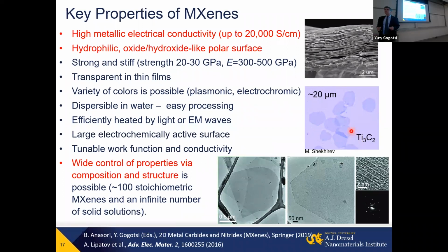You can look at all the literature, all the thousands of studies, for example, on molybdenum disulfide or other materials produced in solution, except graphene. And you will never see flakes larger than, say, a micron in size, because just vibrations in a fluid break them apart. And the strength of MXenes, an indirect consequence of this, leads to the possibility to grow larger flakes for device applications and other things. But otherwise, they look like other 2D materials.